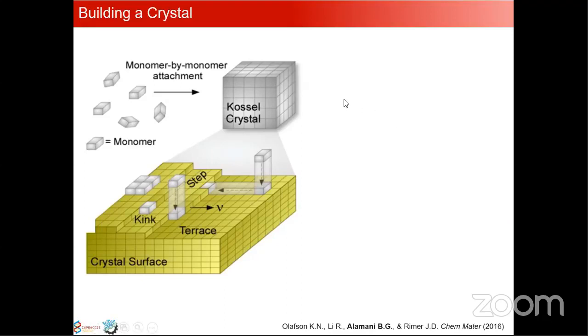Okay. So there was no transformation from one crystal phase to another. Though it's not presented here, we did subject this to XRD, and there was no transformation in the crystal. We did not come up with a new polymorph, because we've also seen in DFT that the zinc actually does not get incorporated into the bulk crystal that we are growing. It just resides on the interface, and once you wash it with water, the zinc just goes away, and you can actually recover the original morphology, even though there's a slight change in the surface morphology.